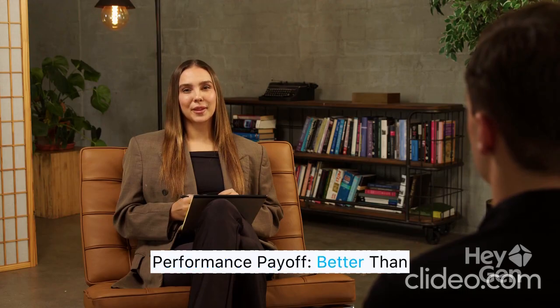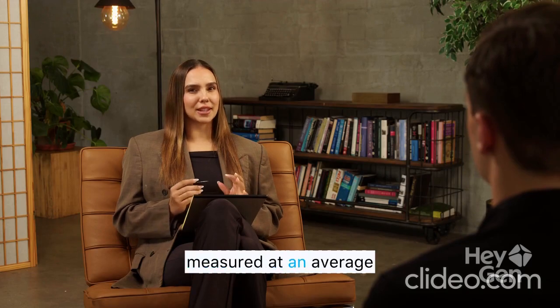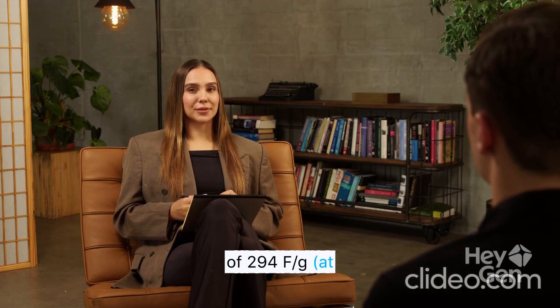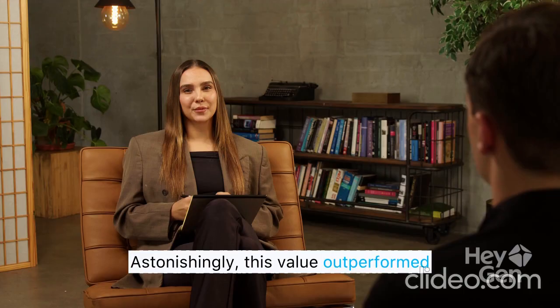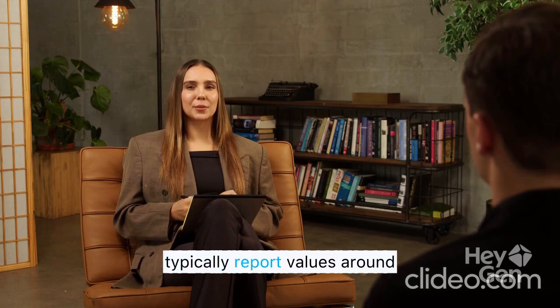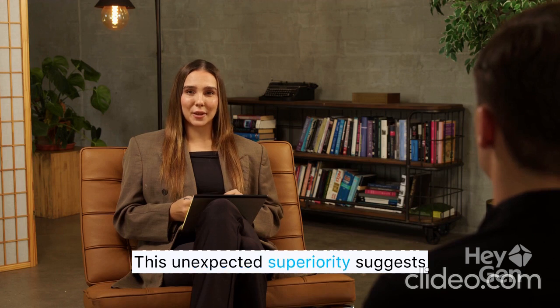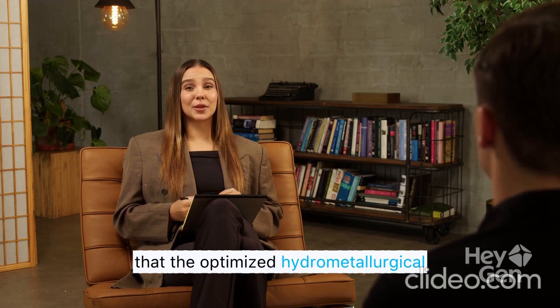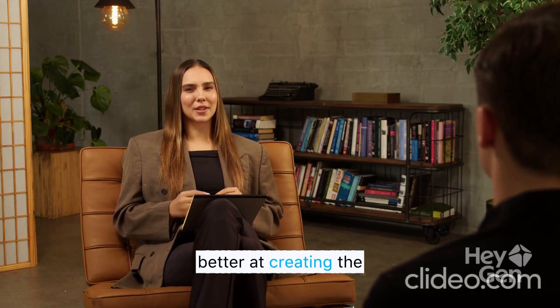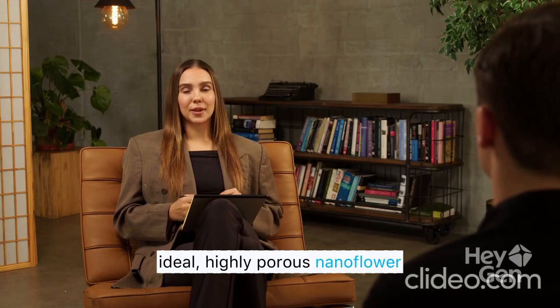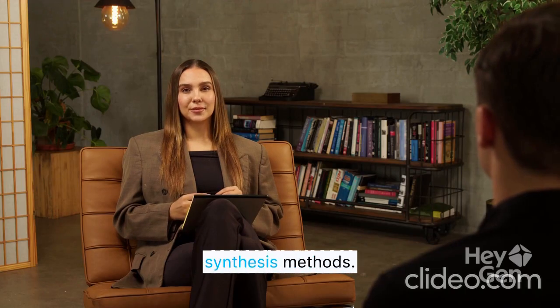Performance payoff, better than pure. The core performance metric, the specific capacitance, was measured at an average of 294 F/g at a 10 mV/s scan rate. Astonishingly, this value outperformed MnO2 synthesized from pristine, chemically pure materials, which typically report values around 237 F/g. This unexpected superiority suggests that the optimized hydrometallurgical recovery process, especially the electrowinning step, might be better at creating the ideal, highly porous nanoflower structure than typical lab synthesis methods.